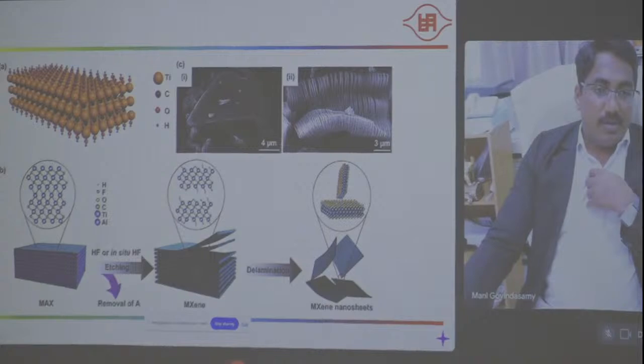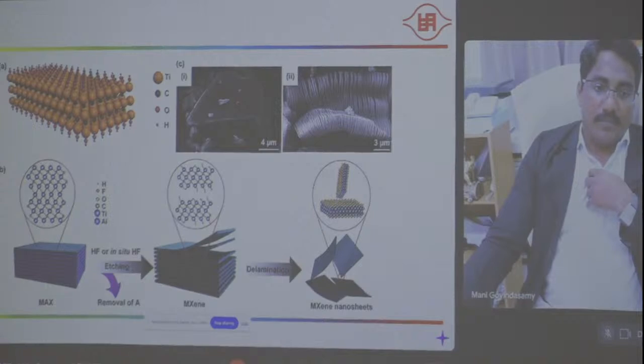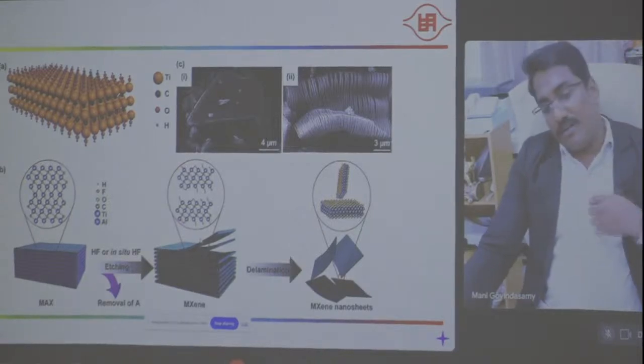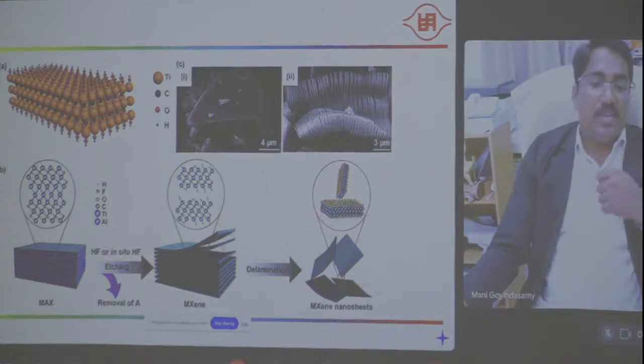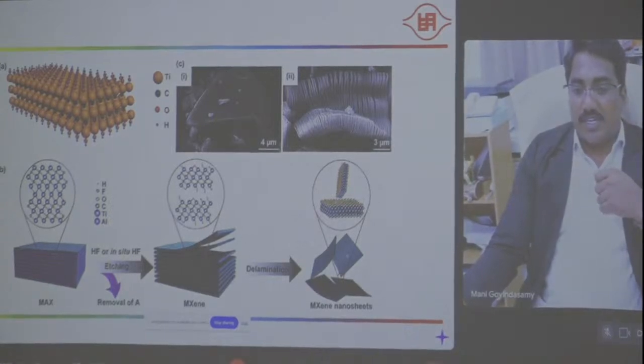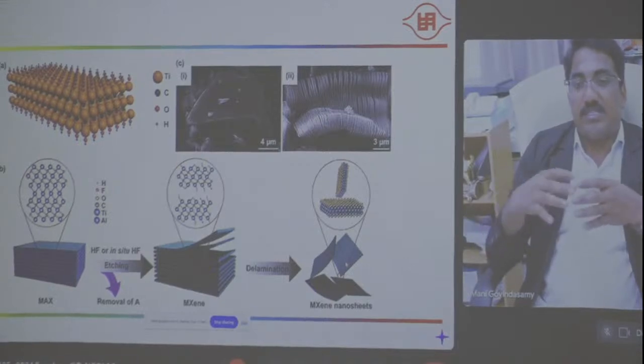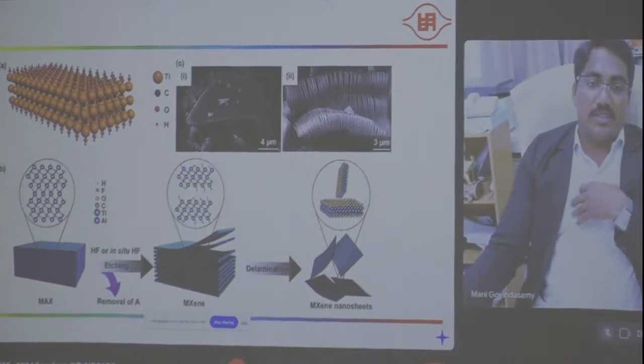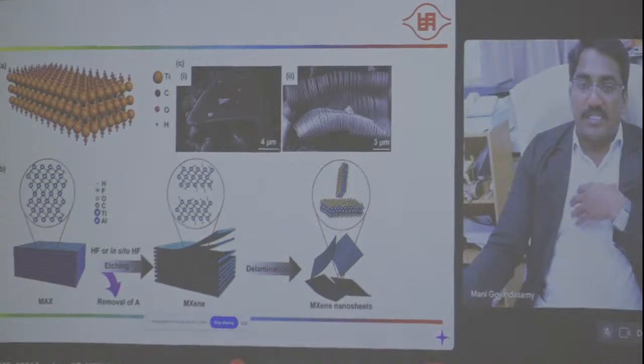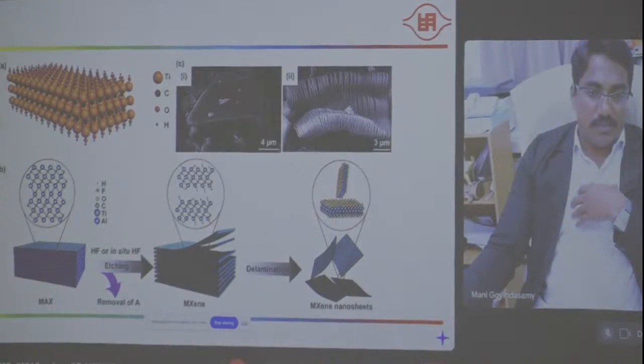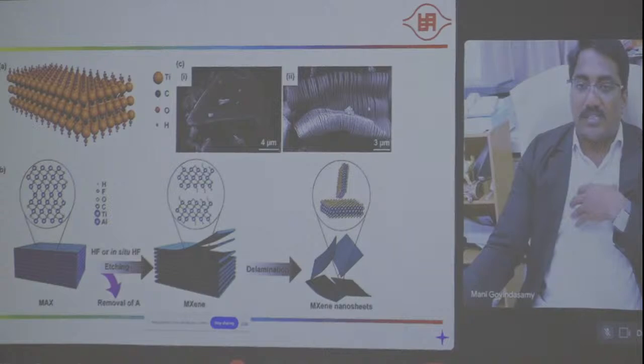For example, HF etching is the normal technique, and then we can remove the A, here the aluminium. Once we remove the aluminium, we can get the titanium carbide, then the delamination process. Based on the delamination process, we can get the different layers. See here, this one is the MAX phase. After the MXene, it will be separated into different layers. After this process, we can get it like this.